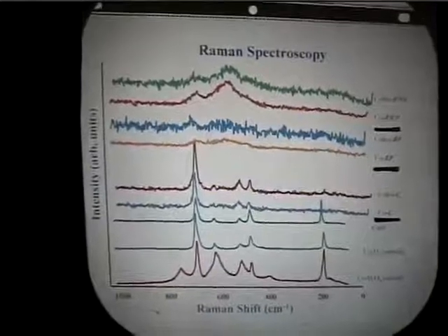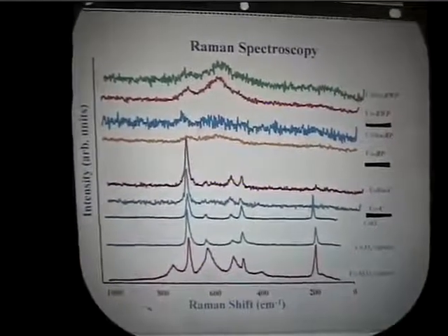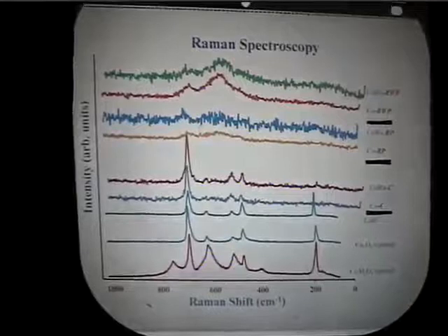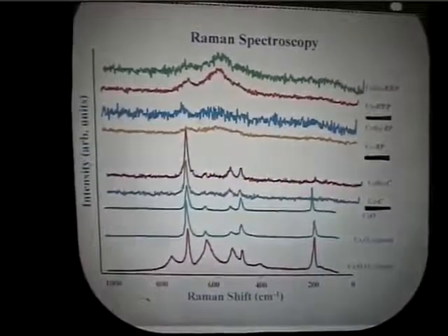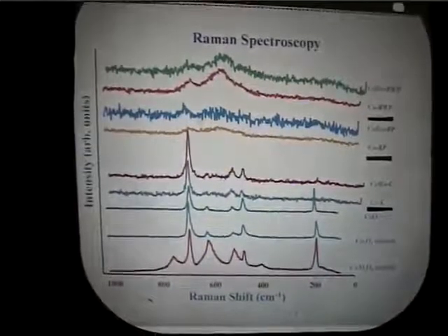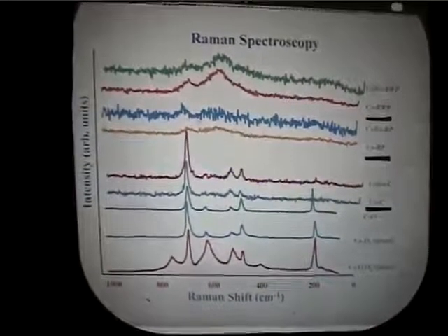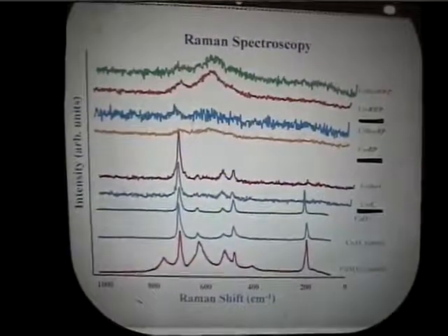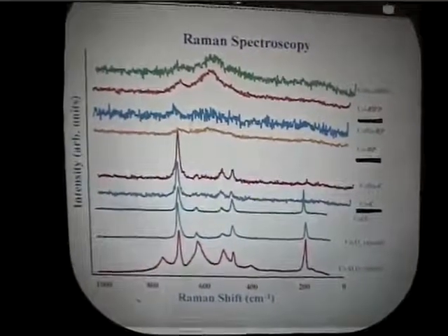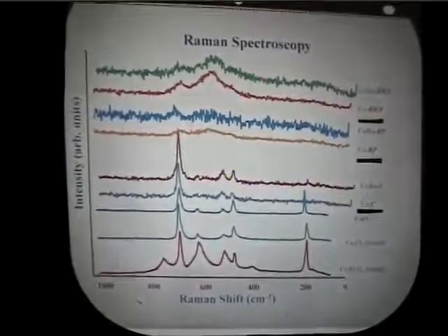We can see that the peak area increases with the additional water vapor during reduction and decreases with ruthenium promotion. And we know from TPR results that the amount of cobalt support compound formation also increases with the additional water vapor during reduction and decreases with ruthenium promotion.